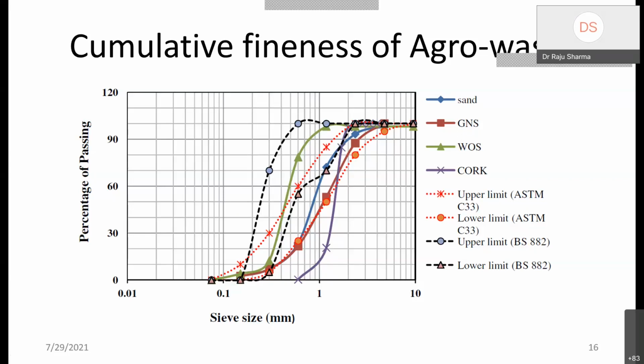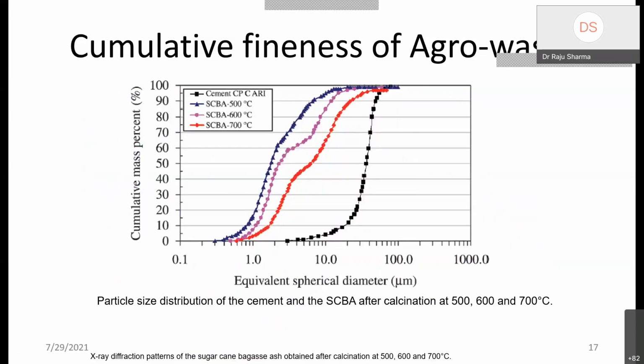Okay, and you see that the upper limit as per the British standard is very, very high, meaning on the lower side the percentage fineness is very high; they are demanding that. So you can see that here 100% of particles are lying about 0.6 mm. But at this range, you can see that only 60% of the upper limit of ASTM C33 is here, and here you can see that 100% have passed. So these are the different technical aspects of different countries' codes, right? They use them accordingly.